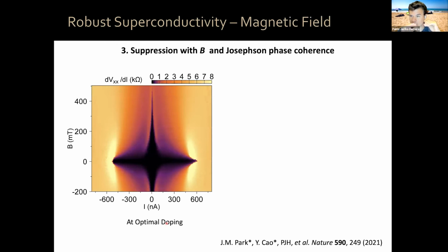Now, you also want to see what happens in a magnetic field. So if you are near optimal doping, where superconductivity is very robust, if you measure the differential resistance as a function of current bias and magnetic field perpendicular to the plane, then you can see, black means critical current. So I mean, the region of superconductivity. So you have this critical current, which has a long tail, gets initially suppressed on a 100 millitesla scale, but then it has a long tail up to about half a Tesla.